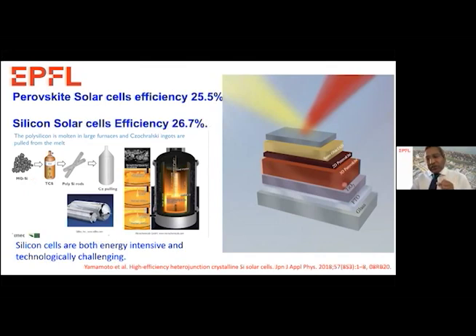So here what we do is perovskite use solution process between two layers. One on the bottom is called the electron transport layer. On the top, we have a hole transporting material. When you excite these perovskite materials, they create charges, positive and negative. The positive charges go to the hole transporting material and negative electrons go to the electron transport material. This way you collect all these charges at the interfaces. The beauty of this material is that when you excite the perovskite solar cell, the creation of charges is instantaneous. In the next two slides, I will explain what I mean by instantaneous creation of charges. That's how the solar cell works.